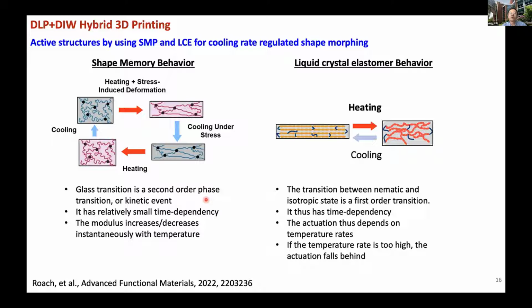If you look at thermodynamics or polymer physics, the glass transition is a second order phase transition. It's a kinetic event, a change of mobility, so it has relatively small time dependency. If your temperature rises, the material becomes soft immediately. If you lower the temperature, without considering heat transfer, the material immediately becomes stiff.